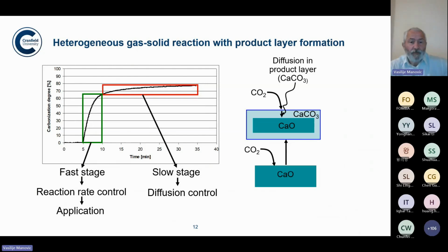Another interesting thing about solid-based sorbent, specifically if we are talking about calcium oxide, is that when we look at the kinetics of the reaction, we have 2 stages. At the beginning, if we expose calcium oxide at high temperature to CO2, it reacts very quickly in the first few minutes. But after that, there is almost no reaction or a very slow reaction. At the beginning, we have a reaction rate controlled reaction, and when we are designing processes, we are only considering this, because it would not be practical to wait for days or hours to capture a few more percent of CO2. That second stage is slow and diffusion controlled.